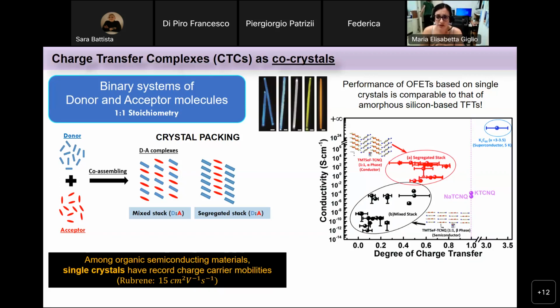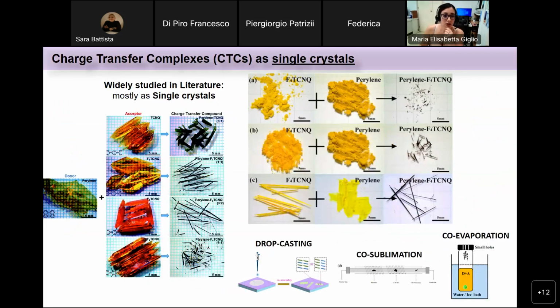And as I told you, by tuning the degree of charge transfer, we can tune the conductivity of the material and also the properties, but also the supramolecular structure has an impact on this. And we can see in this graph that there is a clear separation, in terms of conductivity, between the segregated stack configuration and the mixed stack. So, charge transfer complexes have been widely studied in literature, but mostly as single crystals produced by drop casting techniques, co-sublimation of the parent compounds, or co-evaporation.